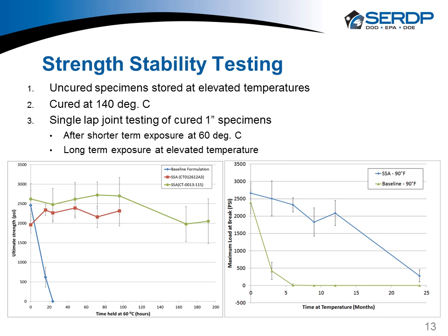After about 3 months, the unencapsulated Fenuron, the baseline, which you see in the green line, started to cure, and the vast majority of the mechanical strength had diminished. The shelf-stable variant, you see in the blue line, had much better stability for a year.